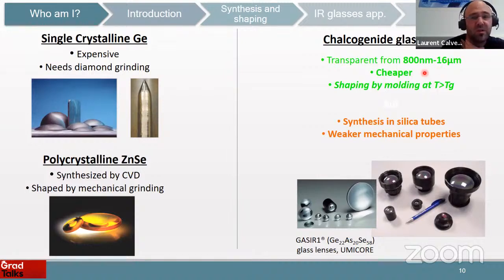They are cheaper because they will use less germanium. And also what is very interesting with glasses, compared to the other materials, is that you can shape them by molding at a very low temperature, just above the glass transition temperature. The main drawback of this material is that you have to make the synthesis in silica tubes. The silica tubes are single-use, so you have to bring them and take back the glass. And also, this kind of glass presents very weak mechanical properties compared to window glass.